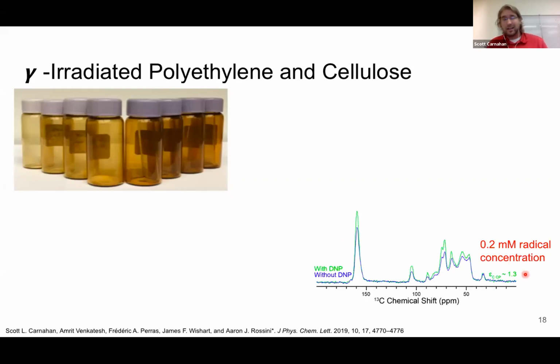So this kind of says I can just take something, especially if it's a polymer, gamma radiate it and run it, and I should be able to get some sort of enhancement. There's still room for a lot of better optimization here. I took one that had 0.2 millimolar, which is one of the samples over here on the left side. I did not take one of the higher dosed samples, so there's lots of room for optimization here.